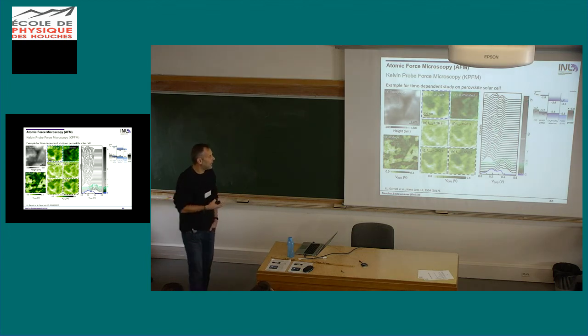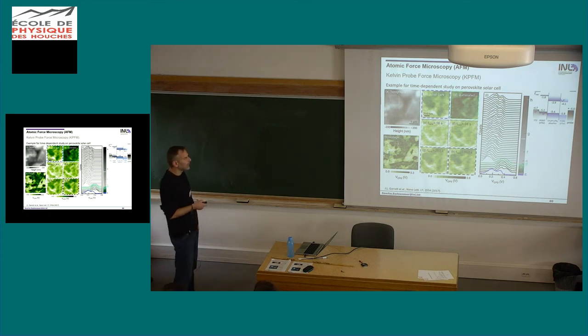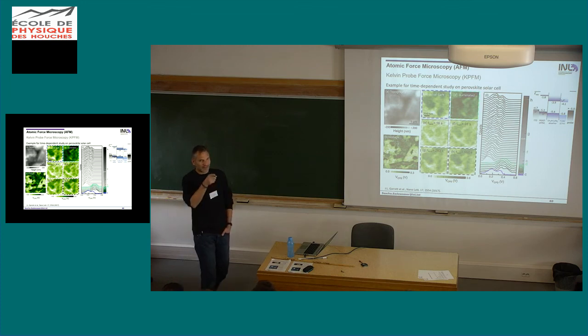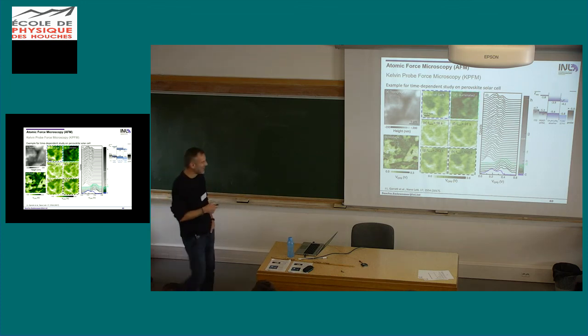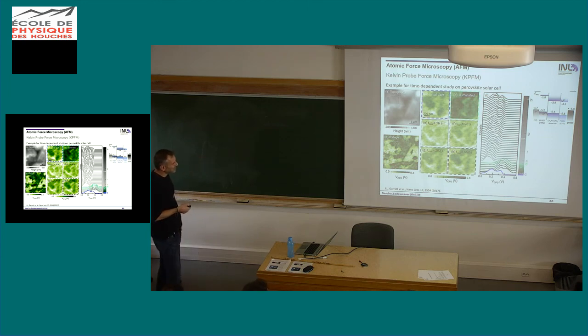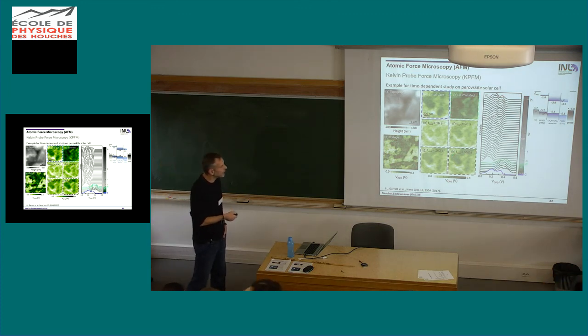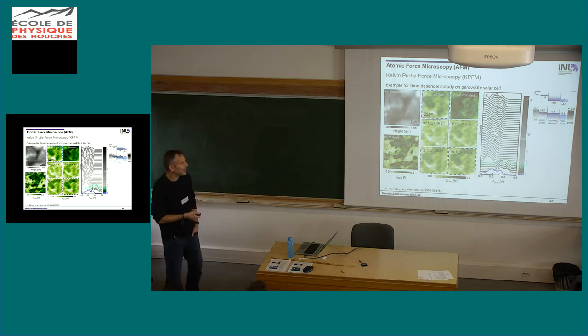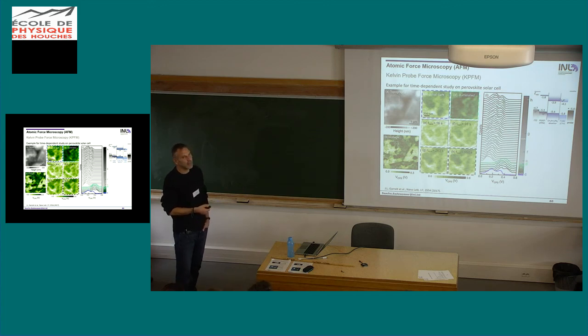And what they explained is that, and I'm not an expert on perovskites, but if you have questions, there's one there, at least one. So what they explained is that the changes that happen very quickly are electronic changes, whereas the changes that happen on this time scale of tens and hundreds of seconds are ionic movements. So this causes this change. Of course, this is an indirect interpretation. They cannot completely prove that, but they can correlate this to timescales measured in other experiments.